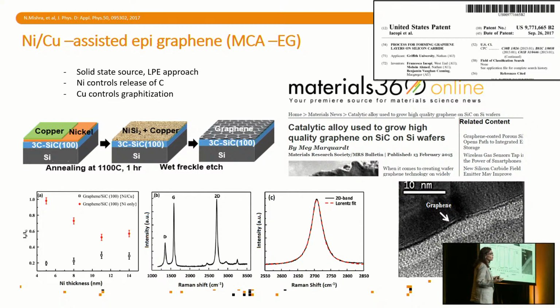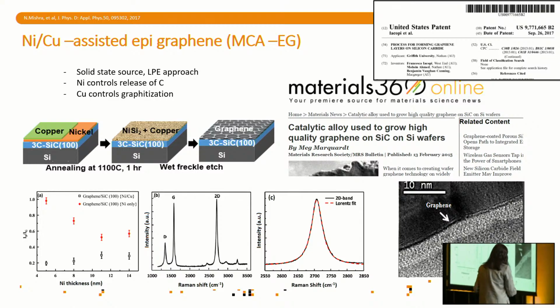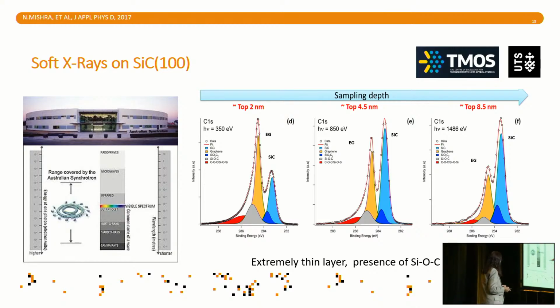And it is known to work much better, especially in the presence of defects, because you will have a much longer diffusion length for the atoms that are trying to find their best position in the lattice. So that releases a lot of the restraints, it doesn't eliminate them, okay? But it releases a lot of the restraints that are coming from the defects on the silicon carbide. And you can see here, we go from nickel only up to here, an ID over IG of 1, so really high, down to here, 0.2, which is not perfect, but this is the difference between a continuous graphene with reasonable grain size at about 100 nanometers, which I'll show you what that does, and something that is patchy and doesn't do much at all, okay?